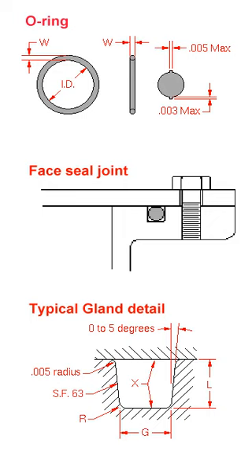Nitrile rubber NBR, HNBR, BUNA-N is a common material for O-rings because of its good mechanical properties, its resistance to lubricants and greases, and its relatively low cost. The physical and chemical resistance properties of NBR materials are determined by the acrylonitrile content of the base polymer. Low content ensures good flexibility at low temperatures, but offers limited resistance to oils and fuels. As the ACN content increases, the low temperature flexibility reduces and the resistance to oils and fuels improves. Peroxide cured materials have improved physical properties, chemical resistance and thermal properties.